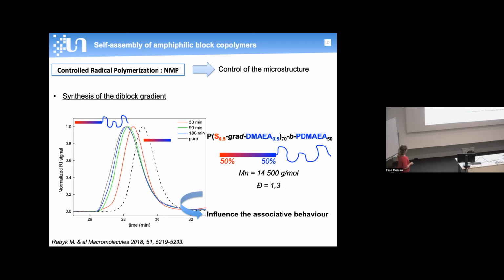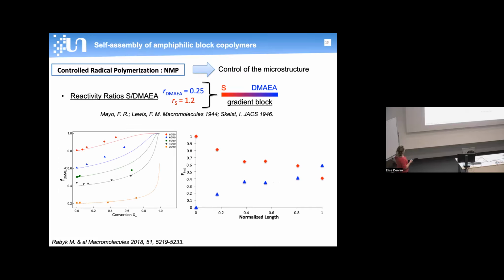So what is very important in this area is that the control of the chemical structure and composition of the polymer is highly important because it will influence the self-assembly and physicochemical property in solution. So that's why we always use a controlled radical polymerization to design our copolymer, and in this case it was nitroxide mediated polymerization, and we could synthesize well-defined block copolymer with narrow molecular weight distribution. And we studied the microstructure inside the hydrophobic block, which is a copolymer of more styrene at the beginning and more dimethylaminoethyl acrylate at the end of the block, by the determination of the reactivity ratio of both units.